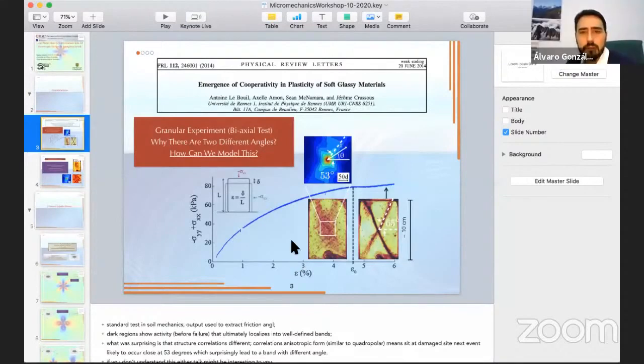Kamran, how is this deformation seen in these experiments? Is it also a photoelastic material seen through a polarizer? No, they are not photoelastic. As a matter of fact, they are opaque glassy beads, very tiny, maybe of the order of 100 micron size. They have a source that shines laser light on the sample, which gets scattered, and a high-speed camera that records the intensity of each frame. By doing cross correlation between the intensity fields taken at different frames, they get these correlation or deformation fields.